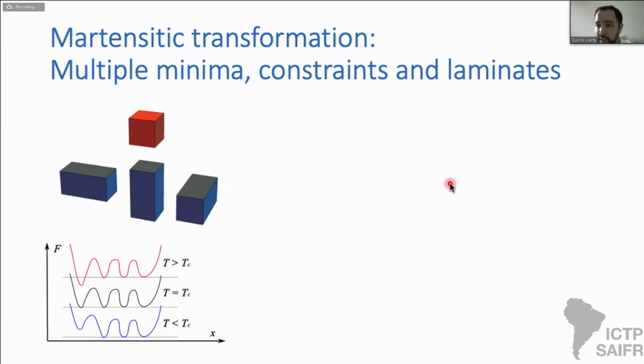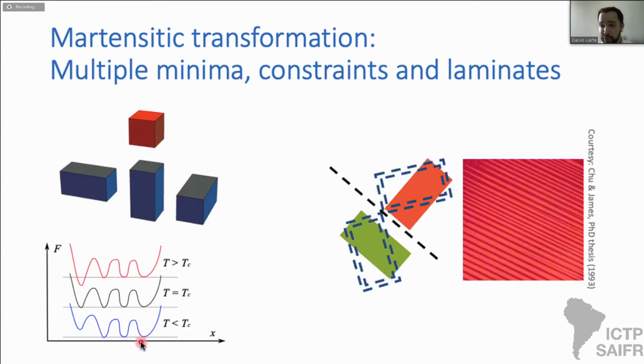And if you look at the free energy landscape of the system, there is a single global minimum for T greater than Tc, as shown here. And then there is a first order solid to solid transformation leading to three minima for T smaller than Tc. Now suppose you let your crystal undergo such phase transformation while you constrain the boundaries of the system so that there is no net strain. Some regions would like to deform along one direction, other regions will deform along other directions. And near the boundary of these regions, these variants will rotate and form these twin boundaries and fine laminate structures to accommodate the cell deformations under constrained boundary conditions. You can actually see these twin boundaries using experiments, for instance, as shown here.